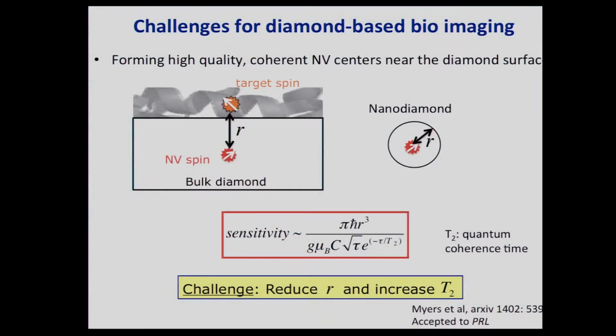So here, if one were to take a bulk diamond, if let's say you have some target spins that you're trying to do magnetic resonance imaging on, or if it's a current flowing down a neuron, you still want your sensor to be quite close to that source of magnetic field. Or in this case, if there was a nanodiamond with something around it, likewise, your sensitivity to magnetic fields is given by this equation. The important things to note here are it goes as the distance cubed and the coherence time, the quantum coherence time. So really one wants to have small r's and long T2s. But these traditionally don't go hand in hand. The closer you bring your NV center to the surface, the worse it gets. And so this is a challenge that a lot of the people, in particular in my group, are really focusing on.